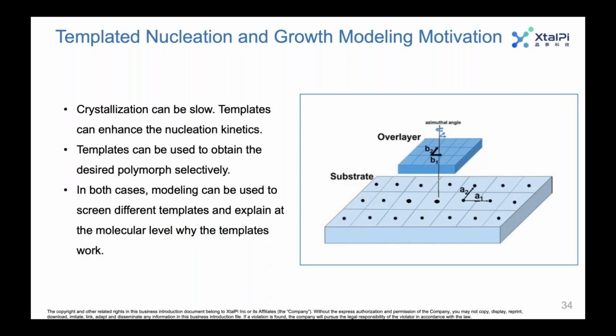So what would be the motivation for modeling templated nucleation and growth? Well, first of all, crystallization can be slow, but templates can enhance the nucleation kinetics. So templates can be used to grow crystals faster, right? Which could be a benefit for process. Also, templates can be used to obtain desired polymorphs selectively. So if you have competition during crystallization or a particular form you want to target, you could potentially use templates to try and target crystallization of a select form.